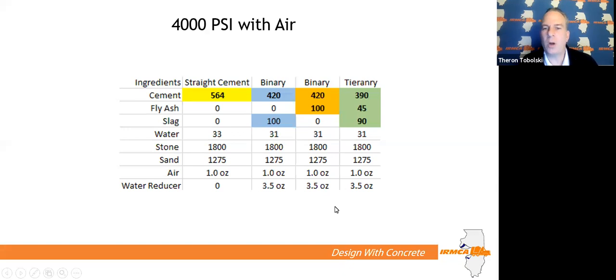You can also do what they call a ternary mix. A ternary mix just means that there's 3 cementitious materials in your concrete mix. There's 390 pounds of cement, 45 pounds of fly ash, and 90 pounds of slag, 31 gallons of water, and we also add 3.5 ounces of a water reducer. These mixes are all going to perform well. They're all going to be freeze-thaw durable, and they're all going to achieve the 4,000 PSI specification that you wanted.